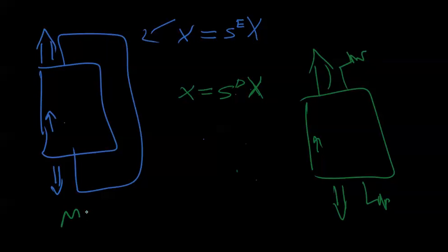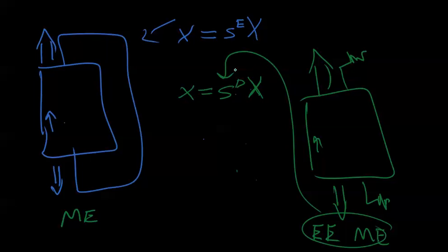In this one, we're only storing mechanical energy. In this, we're storing electrical energy and mechanical energy. But both of these terms are hidden inside of this, because when you're pulling on it, you're feeling the pulling, but the pulling is creating both electrical energy and mechanical energy. So you're doing two things at once, but you don't really know what you're doing. It feels like you're pulling really hard, even though two types of energies are being stored. So which is higher? Now you may get this answer wrong. SE is higher. But I think I tricked you a little bit.